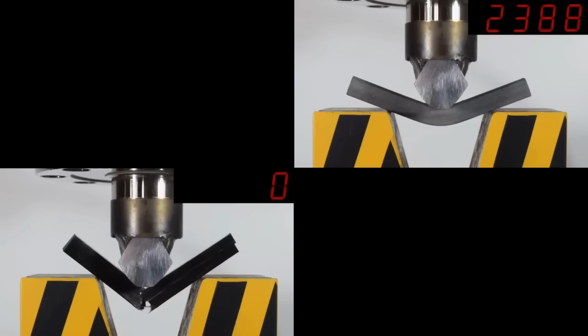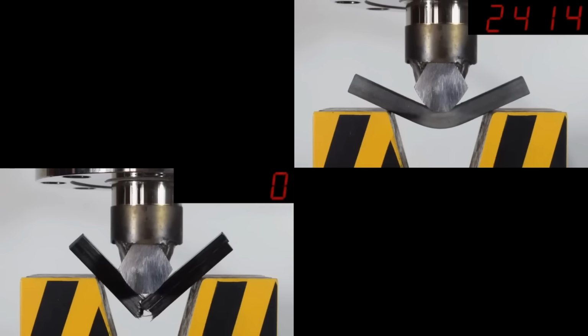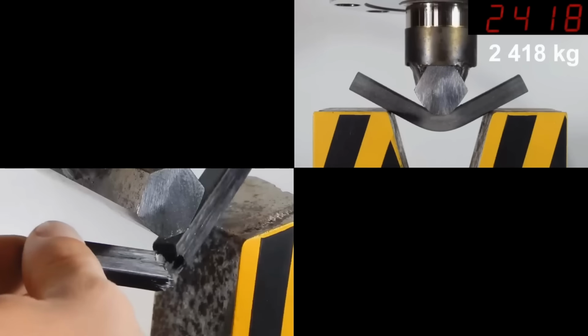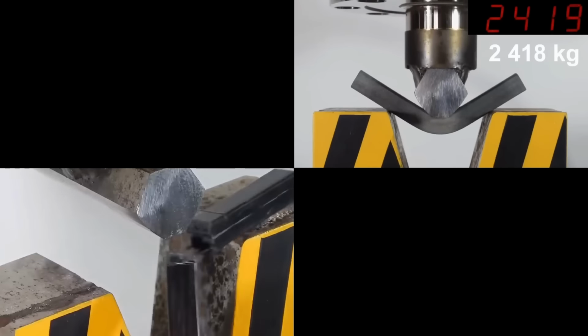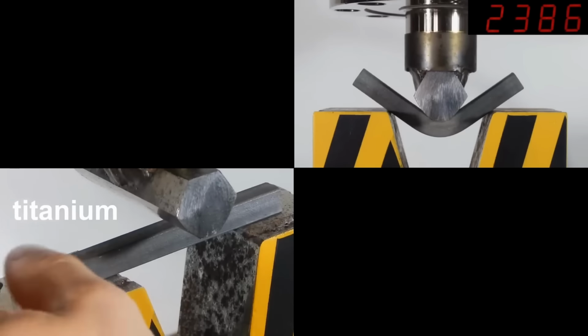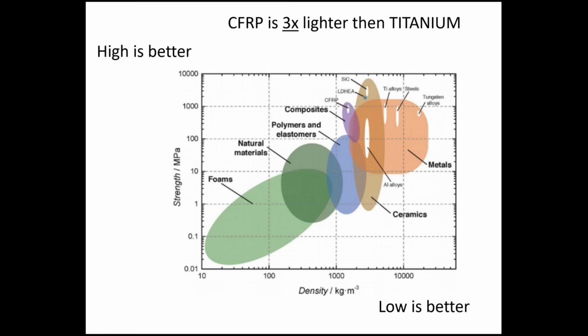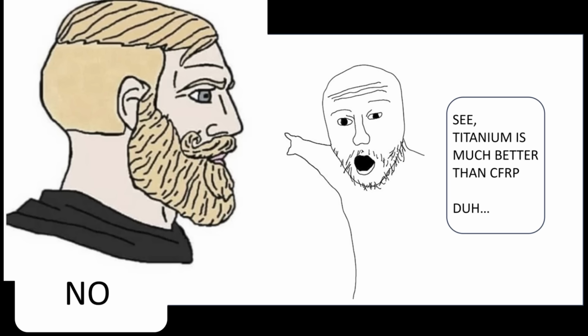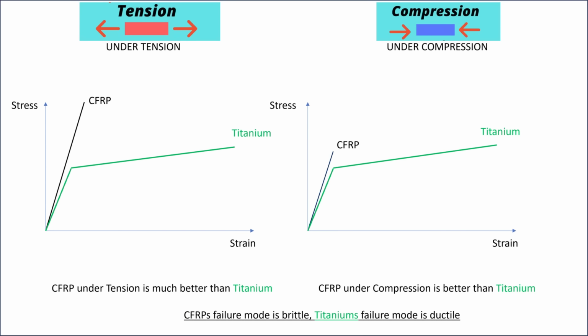From the looks of it, both test specimens are about the same dimensions. Titanium carries 3 times the load until failure compared to CFRP, but titanium is also about 3 times heavier. So in terms of load-to-weight ratio, both materials are about the same in this 3-point bending test scenario. In a pure tension test scenario, CFRP can handle about twice the load of titanium. In a pure compression test scenario, it is about as good as titanium.